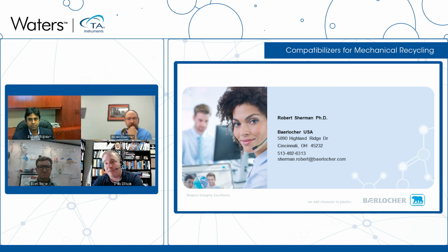And you're looking for smaller dispersed phases in systems which contain compatibilizers compared to without. And then those systems will generally, if the compatibilizer is at the interface and of sufficient molecular weight to stabilize the system, this dispersed phase will remain small. It will not coarsen with time. So those kinds of tests we use frequently to infer interfacial activity. And obviously coupled then with mechanical properties, you have a good indication you have a good compatibilizer.